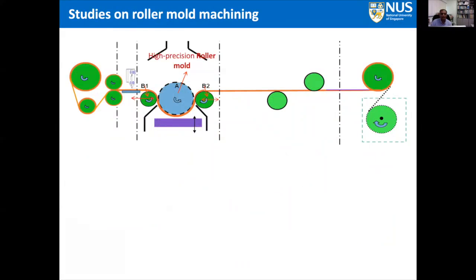So basically, a roller mold consists of the main high precision roller mold at the center, which is A, and we have two smaller rollers, B1 and B2, that are just to create the tension so that the film can pass through it. And the bottom one is where the ink is placed, and the ink copies from the mold onto the polymeric film, so that we can produce whatever pattern that we want, which passes through a dryer so that it dries off, and then we can produce the functional features on the polymer.